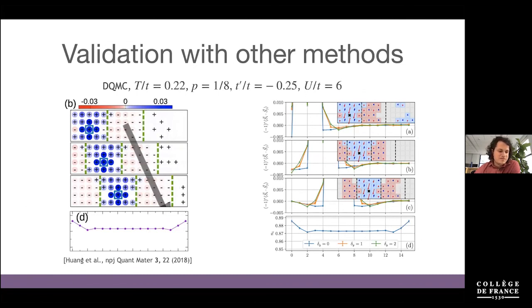And so this was the work I was mentioning before, where Huang et al. find signatures of the stripe phase, this incommensurate spin correlations at finite temperature, and we can exactly reproduce their results without going into too much detail. So for example, here in the lower panel, I'm showing the density on a cylinder of length 16, and it exactly compares with their results here. So for example, this small dip also presented by them. But also these spin correlations, which are shown here in some way, match exactly what they have found.